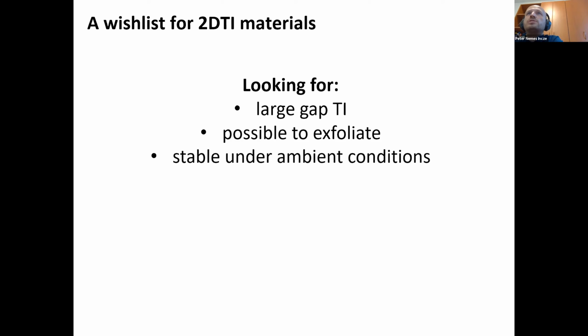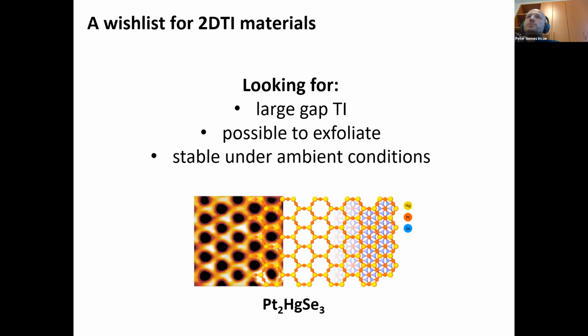Just think of the situation where graphene was not a material that was stable under normal laboratory conditions. You would need, for example, UHV to handle it, or some other exotic lab environment to work with it. So the literature and the field would not have exploded in such a way as it did. So this requirement makes the material available for a lot of different labs and a lot of experiments. And as I will hopefully show you, this material, platinum mercury selenide, fits this wish list quite well.